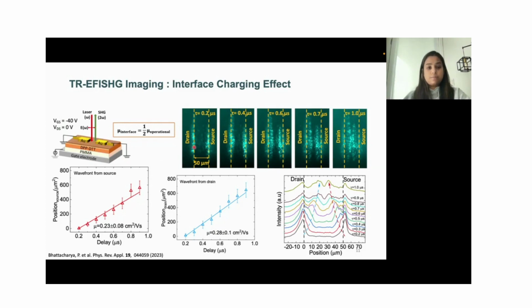charge carriers really happens in terms of injection through the dielectric layer into the interface between the semiconductor and the dielectric. If you look at the images here, going with the transit time, you can see the accumulation of the charge carriers closer to the drain and source electrode, and then eventually the entire accumulation region being formed uniformly from both sides until it is completely formed. And it has been found from the Maxwell-Wagner model that the interface carrier mobility is about half of that obtained from operational mobility.